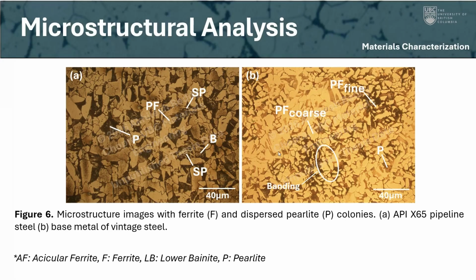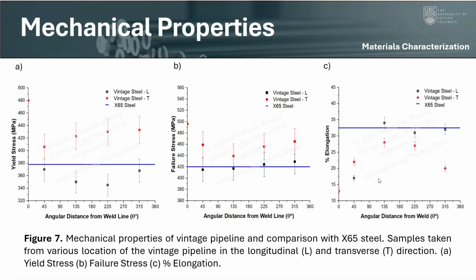Also, there are areas of banding, as I've labeled on the image. So essentially, we can see that this microstructure has a more heterogeneous appearance, and that will correspond to the mechanical properties in the next section. Okay, so from these images, I tested, or I was observing the yield strength, failure strength, and the percentage elongation of our steel dog bone samples for vintage and X65.